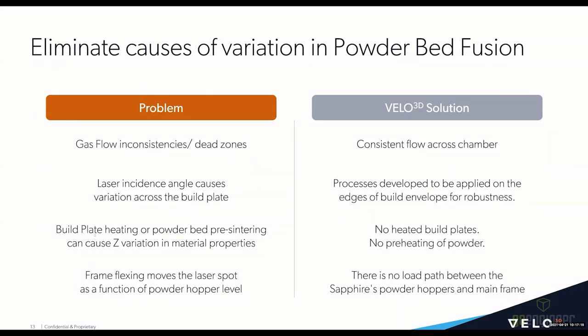Next, there's build plate heating, or powder bed pre-sintering, or build chamber heating that occurs in other systems. And this can cause variation in the Z direction with material properties. You get larger grains towards the bottom, smaller towards the top. At Velo3D though, with our Sapphire, there's no heated build plates. There's no preheating of powder. We do this in order to drive uniformity throughout the build volume.